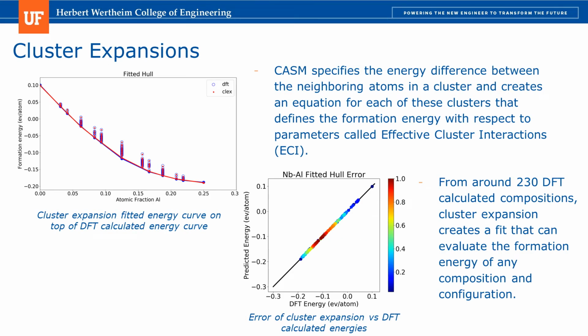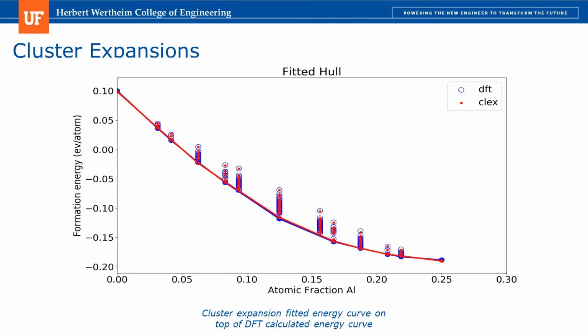Cluster expansion enumerates structures and fits the energies obtained from DFT to predict the formation energy of the system at all necessary compositions. The plot shows the DFT calculated hull in blue and the cluster expansion fitted hull in red.